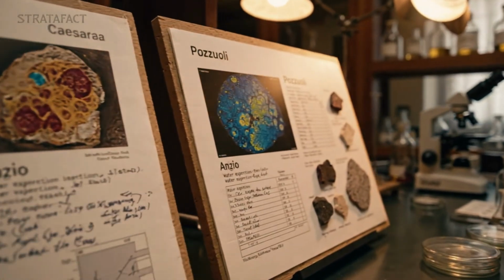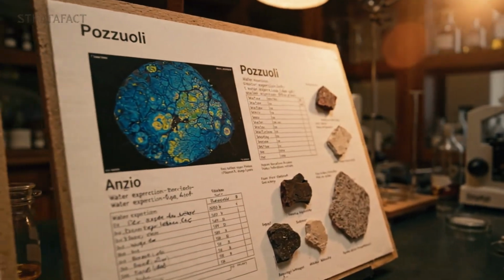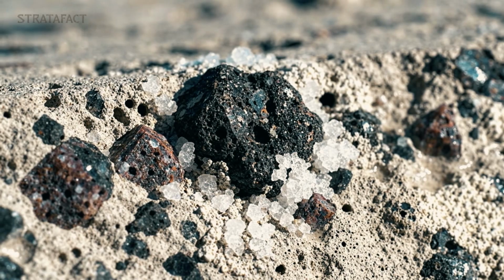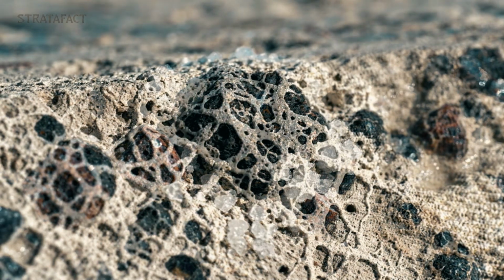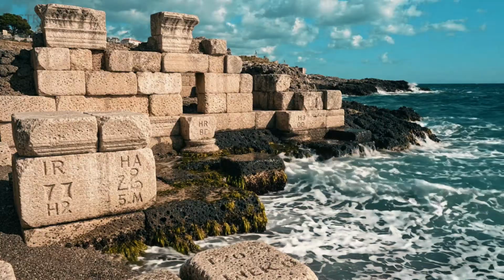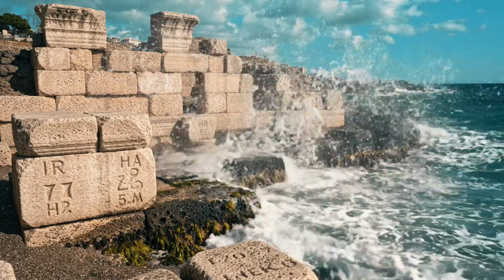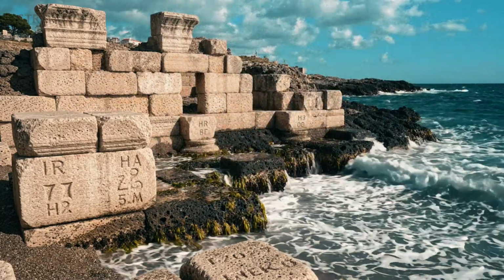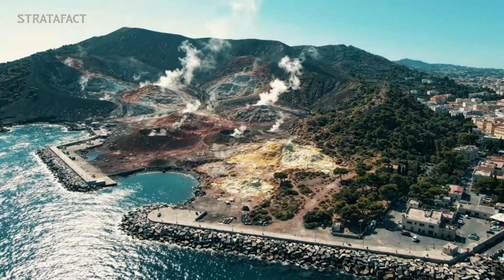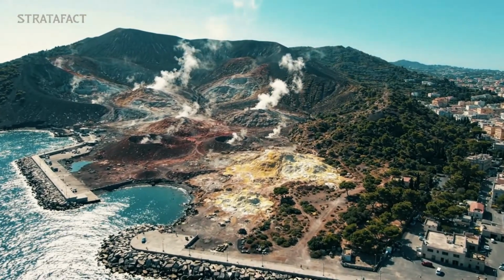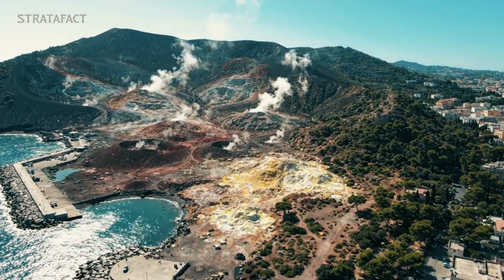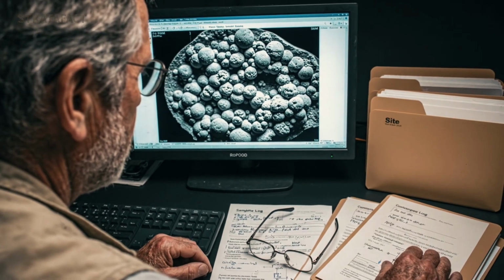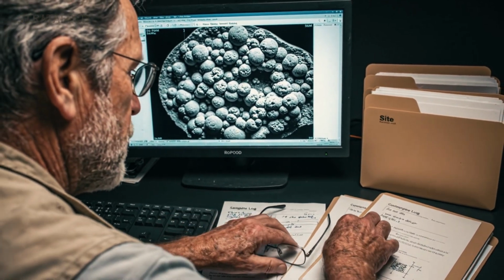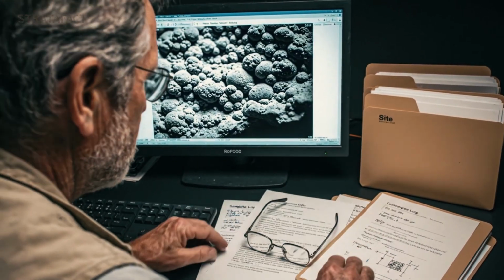The samples from different sites were not identical. The Caesarea material had been submerged in relatively warm, high salinity Mediterranean water for 2,000 years. The Anzio samples came from a site with different wave exposure and different depth. The Pozzuoli breakwaters had been subjected to localized volcanic heating from the still active Campi Flegrei caldera beneath them, a geological condition with no equivalent at the other sites.